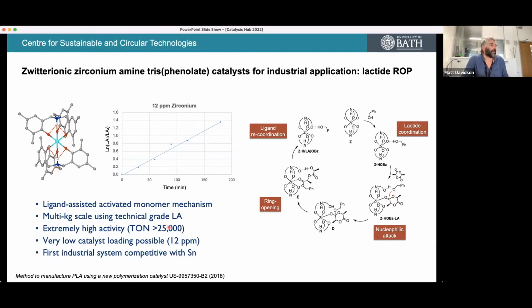We get extremely high activity of these catalysts. We can go down to extremely low loadings under the right sort of formulations. And again, with one of my colleagues at Bath, Antoine Buchard, we've done quite a lot of calculations on these. And we're fairly happy that this is a ligand-assisted activated monomer mechanism in this case, where the trisphenolate can sort of breathe and open up a bit to allow both the initiator and the lactide to come in, and then that can propagate the ring opening polymerization in that way. So that isn't a million miles away from what you might expect with a ring expansion polymerization catalyst.